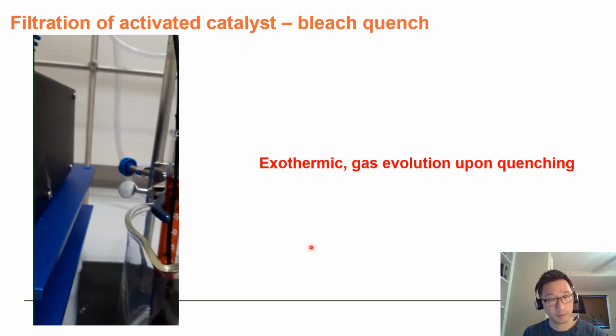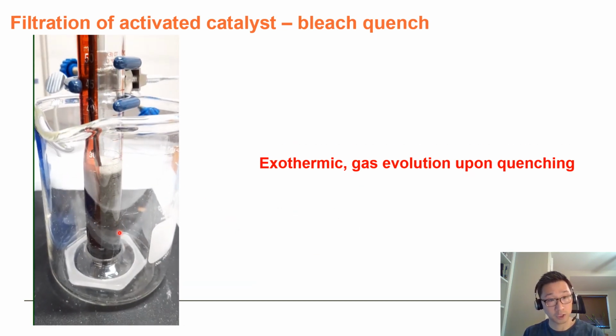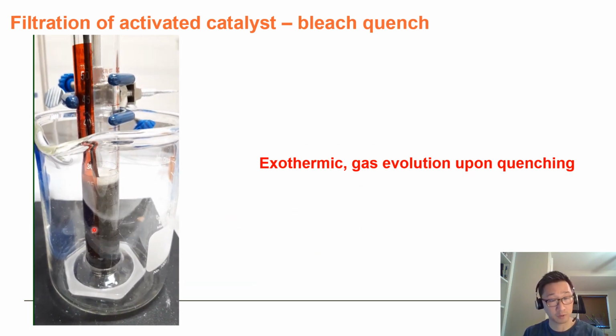Now, I should say, though, that the bleach quench does work. The catalyst, after it's been treated with bleach, is deactivated. However, there are some hazards that are clearly evident just upon qualitative observation, but we wanted a more quantitative evaluation of the hazards of using bleach to quench Raney cobalt.